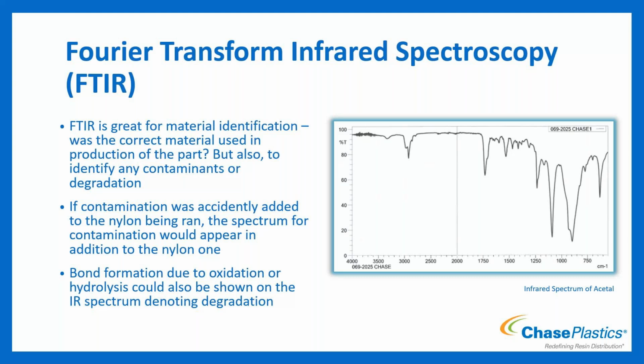Another thing that you can tell from FTIR is when bond formation starts to occur because you have oxidation or hydrolysis. They will also show on the IR spectrum. So when you have some degradation, you'll start to see that. And actually, when we go through some of the testing further in the presentation, I have that degradation shown in an FTIR curve for ABS that was exposed to UV. And so we'll get to that. But if it's degraded enough, you'll see a different part of the spectrum showing up on the FTIR curve.